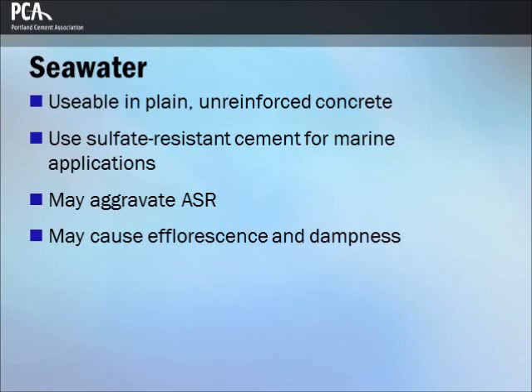Seawater containing up to 35,000 parts per million of dissolved salts is generally suitable as mixing water for concrete not containing reinforcing steel. Seawater is not suitable for use in production of concrete with steel reinforcement, and likewise should not be used in prestressed concrete due to the risk of corrosion of the reinforcement. If seawater is used in plain concrete for marine applications, moderate sulfate-resistant cements — Type 2 or MS — should be used along with a lower water-cement ratio. Seawater should not be used as mixing water for concrete with potentially alkali-silica reactive aggregates, and it also tends to cause efflorescence and dampness on concrete surfaces exposed to air and water.